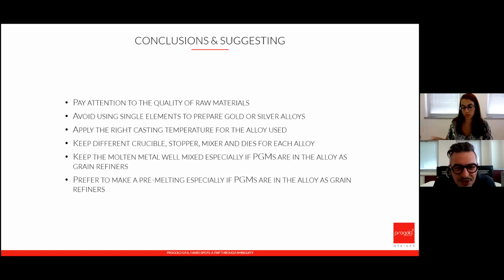Okay, Mr. Artek asks, can casting an alloy with too high a deoxidizer develop more hard spot? So is there any connection? One, it depends on the deoxidizer that we're using, because there are many elements that do the same work, and not all the elements react in the same way. It also depends on the other elements that we have inside the alloy. It's very common in nickel alloys, because nickel alloys tend to have a lot of zinc in them, and they tend to have silicon, as in the cases that I explained. So if you reuse it a lot, of course, zinc is going to evaporate, and if you already have a considerable quantity of the deoxidizer, it's going to become even higher because you're losing some other element.